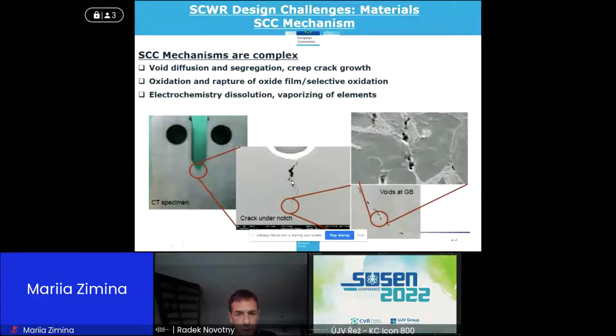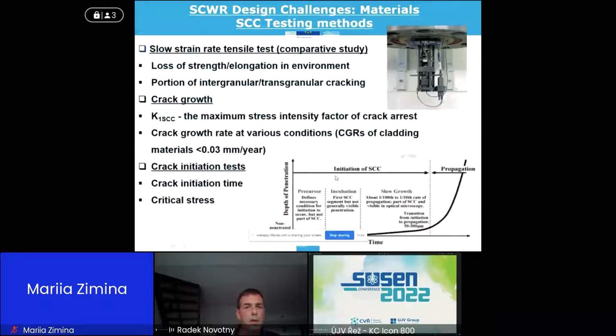As you can see in this example, we have intergranular growth of the crack, and then we can see that in front of the crack tip, we already have coalescence of voids, which later on connect and move the crack farther. So originally, we have the initiation, maybe due to dissolution, electrochemistry, whatever, but then the crack growth is changing a little bit from SCC to creep. So the mechanism is actually joint, creep and SCC.